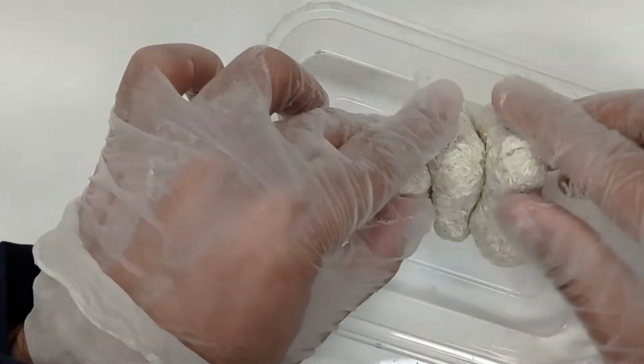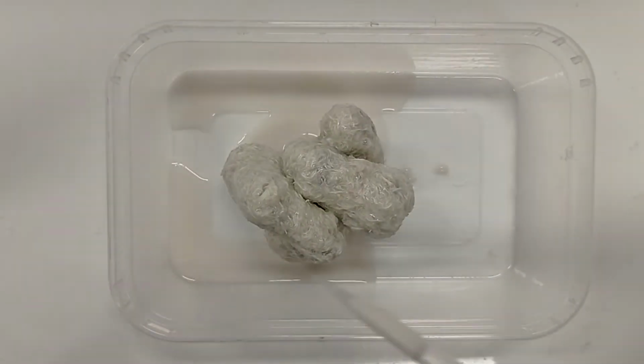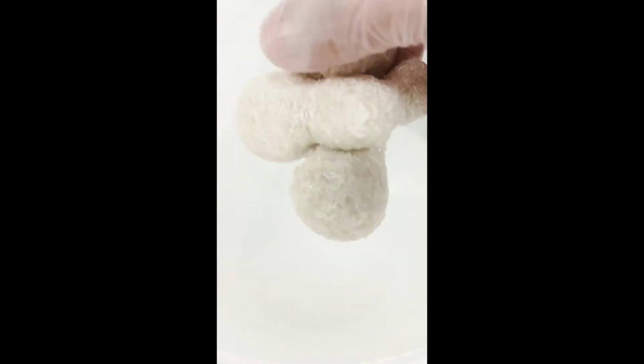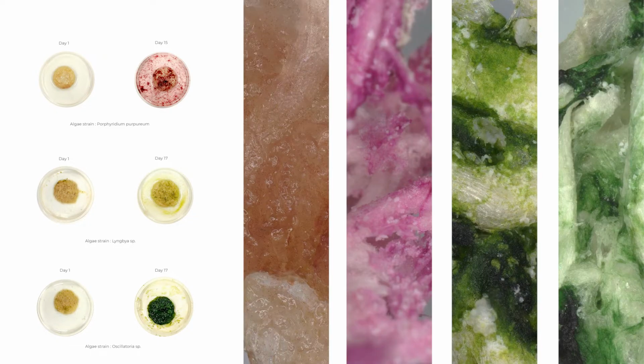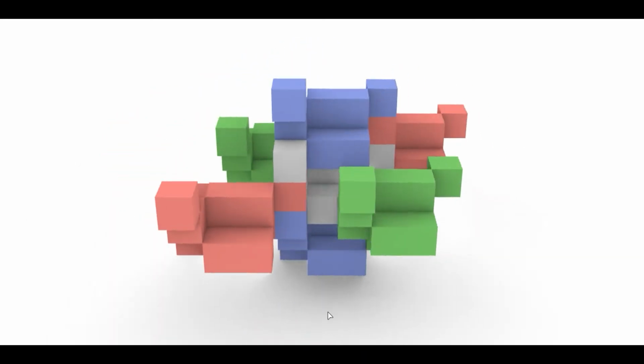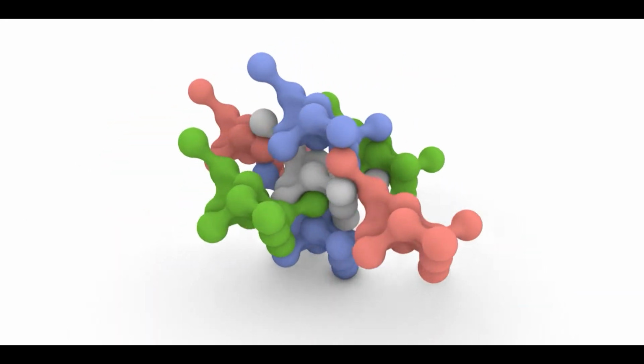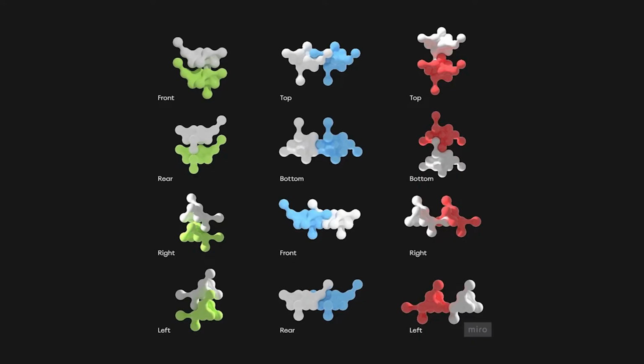Being a hydrogel composite, it has high water absorption capacity, and current tests show that the substrate is immune to deterioration from saline water for a period of more than 3 months. Due to water absorption, it naturally favors algal growth as a substrate and has proven receptive to a series of marine algae. To optimize the functionality of the material application and rethink the design of a traditional brick, we parallelly remodeled the design of the brick so that it can achieve stability on interlocking.